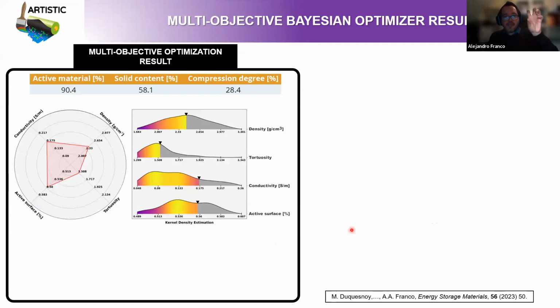Now, if you integrate this machine learning model in this Bayesian optimization algorithm, and you ask this algorithm to optimize four properties simultaneously, conductivity, density, tortuosity factor, and active surface area, this Bayesian optimizer will tell you which manufacturing parameters you need to adopt in order to reach this optimal electrode. And here you see the values that this Bayesian optimizer predicts for the active material content, the formulation, the solid content of the slurry, and the compression degree. This is represented here in red in terms of the properties that are being predicted to be optimal.